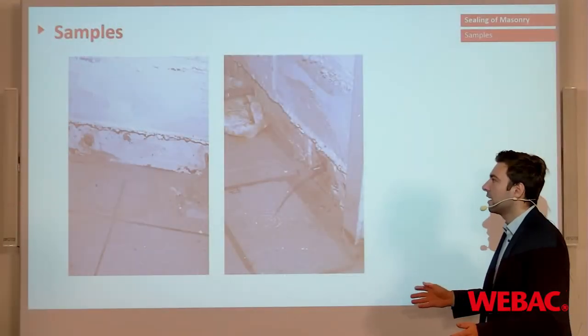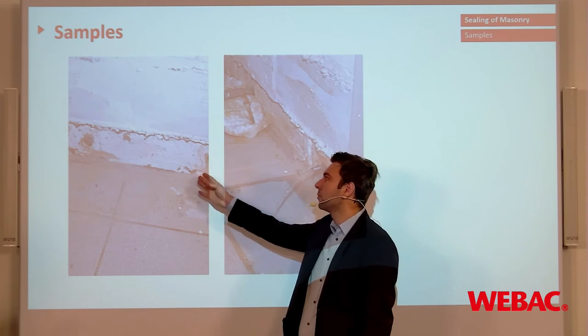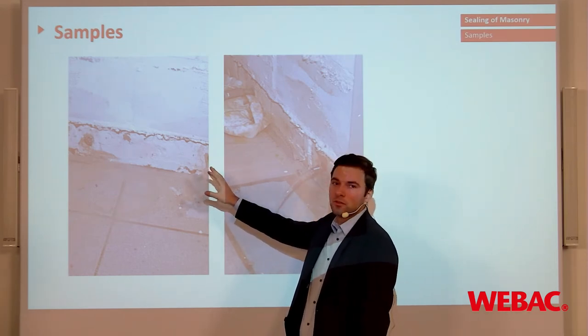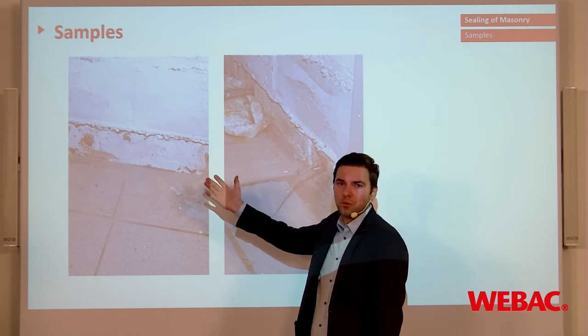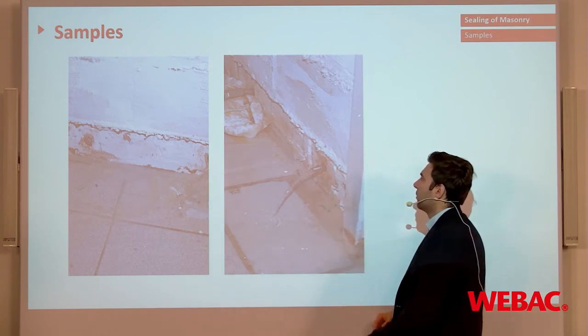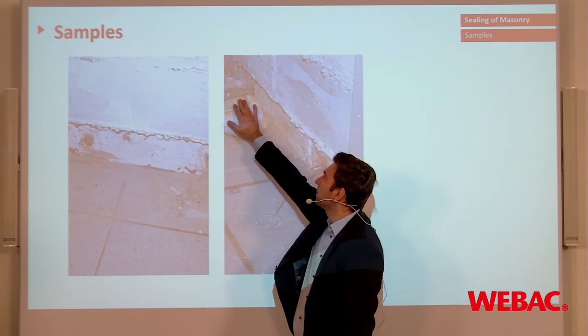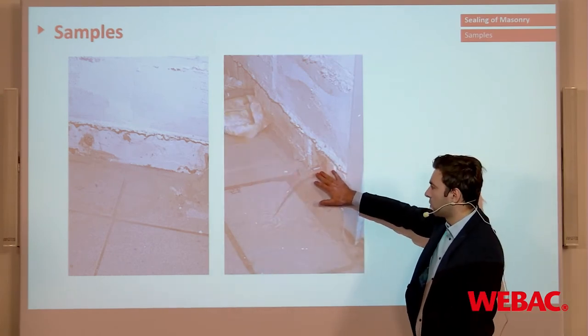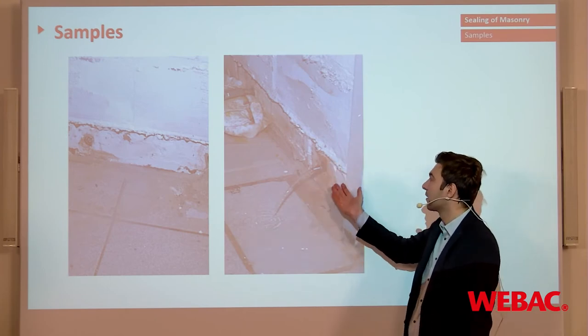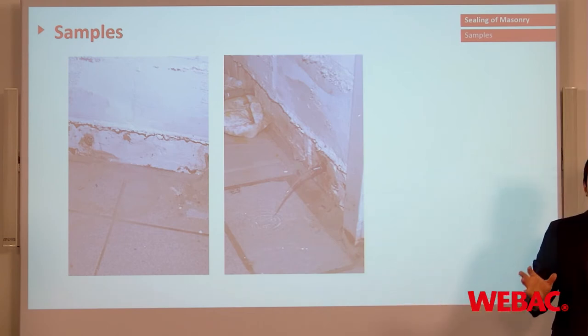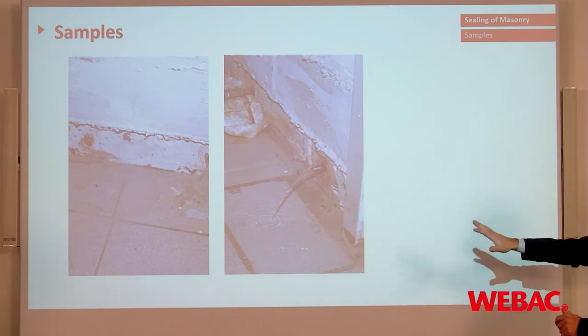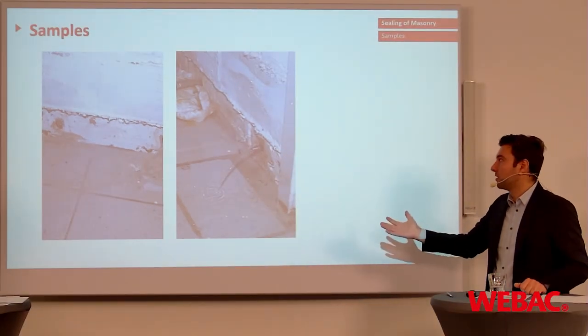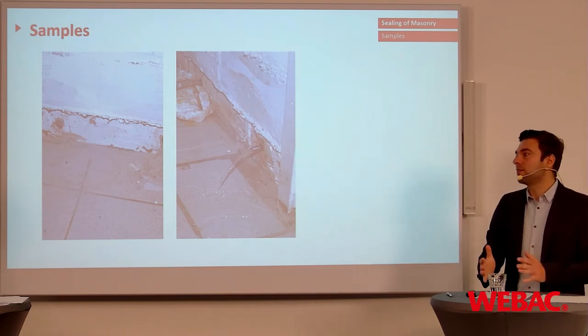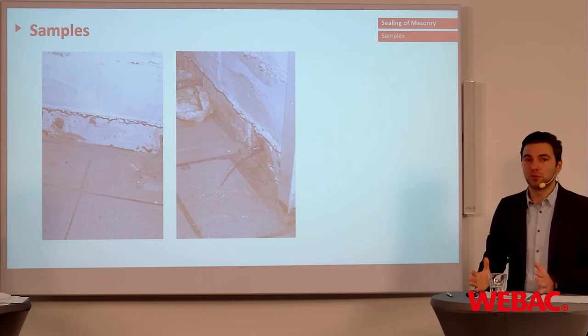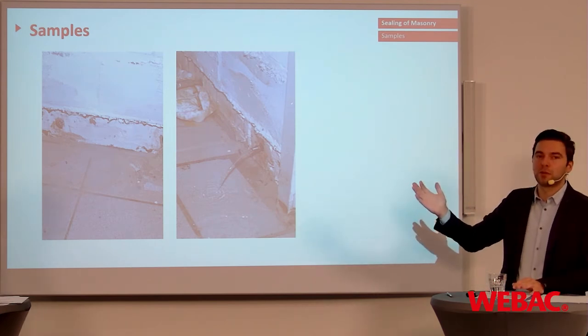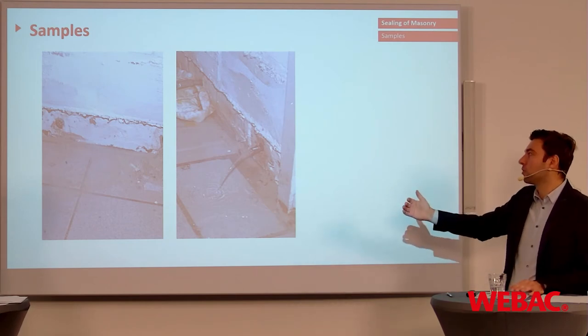So, and now the second example is, once again, you take a look at your masonry, and it looks not that wet. It looks rather dry, and you cannot see, do I really face a problem here or not? And on the right-hand side, you can see that the guy is injecting from that point, and the water is continuously spreading out of the next packer. So you can see that by the pressure injection, you really replace the water inside your structure with the injection material. Just imagine you are now in the case that you are using a non-pressurized system to try to solve this. You just pour in something by gravity, but then you will not be able to push away the water inside the structure.